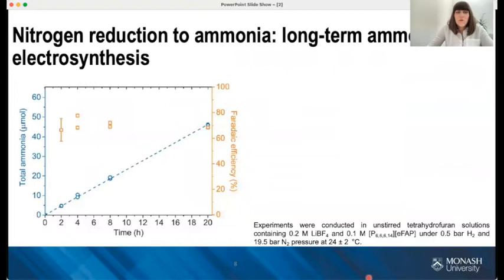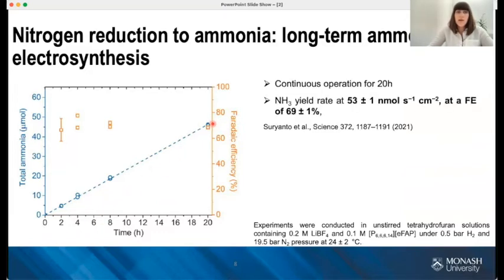But the next key step of that research was to demonstrate that we can run this process for a long, long time, right? So to demonstrate the long-term stability of the proton shuttle and the long-term stability of the whole system, we carried out a series of experiments over 4, 8, and 20 hours in a constant current mode. These experiments are presented here in the figure. They showed very stable operation of the ammonia electrosynthesis system. And the 20-hour experiment produced an average ammonia yield rate of 53 nanomoles per second per centimeter square at a Faraday efficiency of 69%. And this is a really good value.